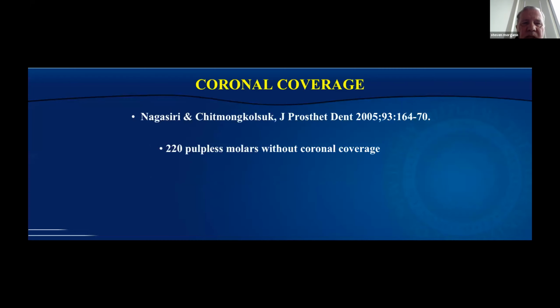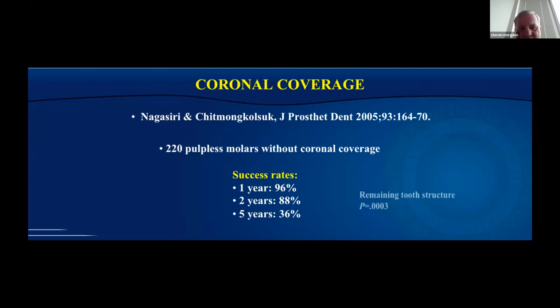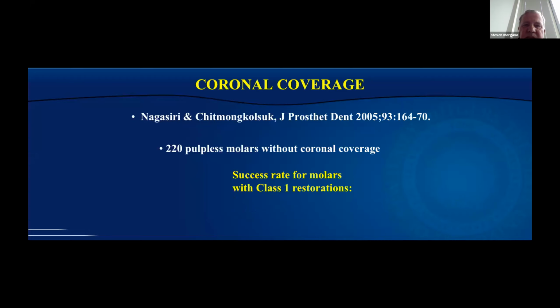Now here's a study on 220 pulpless molars that never got coronal coverage. Now if we look at the success rate after 1 year, not bad, 96%, 2 years, 88%, 3 years, 5 years, 36%. Now the variable that was most significant was remaining tooth structure. But even with remaining tooth structure, they looked at the success rate of molars with just a class 1 restoration, just an access preparation. After 5 years, the success rate was 78%, which means 22% failed after 5 years.